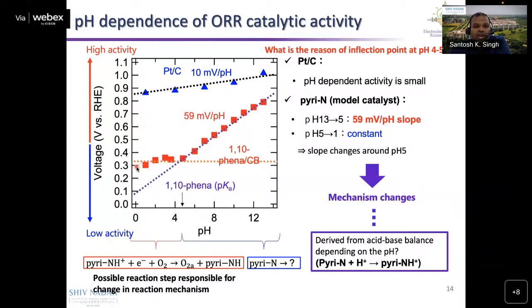When we check the ORR activity of the 1,10-phenanthroline drop over the carbon surface, if you see the onset potential of this catalyst versus the pH of the electrolyte, at nearby pH 5 it shows a deflection point, and after that it follows the 59 millivolt per pH slope. So the question here is why there is a deflection point at pH 5. That is a big question, and that deflection comes from the pK value of the 1,10-phenanthroline, which is also in the range of 5.